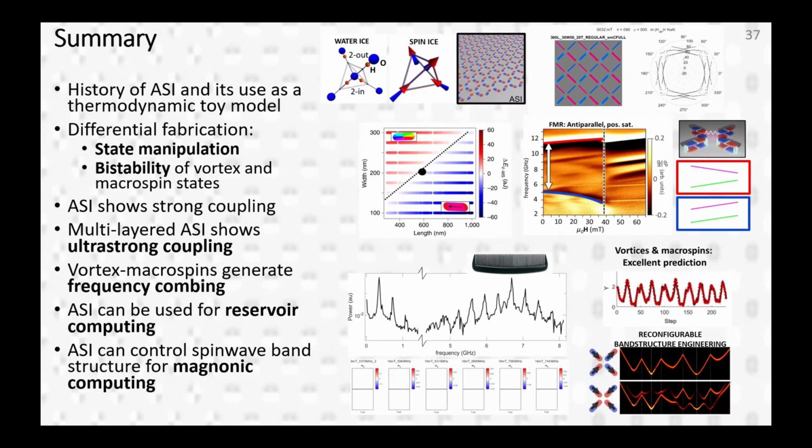So if you make them very long and very wide, you can make them thicker. So essentially you want your thickness to be thinner than that. But usually we don't go higher than 30 to 40 nanometers, because once you start to go higher than that, you increase the sort of out of plane effects, and it's perhaps not desirable. But yeah, usually from a few nanometers to a few tens of nanometers is typical.